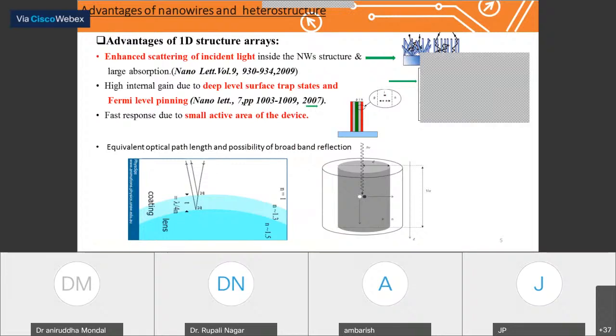In the case of the anti-reflection coating, we normally use thin film based coatings, which have a particular thickness to absorb a particular wavelength. So to absorb a wide band of wavelengths in the solar spectrum, we need to fabricate different thin films of different thicknesses, which basically increases the cost of the devices.